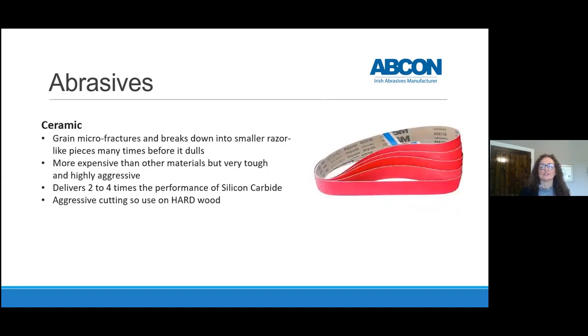Ceramic. So ceramic grain micro fractures and breaks down into smaller razor-like pieces many times before it dulls. It's more expensive than other materials, but it's very tough and highly aggressive. So it delivers 2 to 4 times the performance of silicon carbide, but because it's so aggressive, it would be used on hardwood as opposed to softwood.